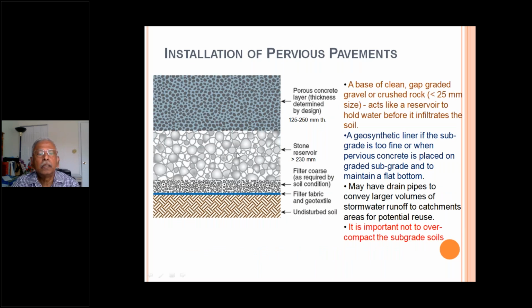So this is a cross section of the pervious concrete installation. This porous concrete layer may be 125 to 250 mm thick, and then you have the subbase, which is very important, where the water is collected. It can be greater than 230 mm. Then there is a filter fabric and geotextile which can be used. It is optional.